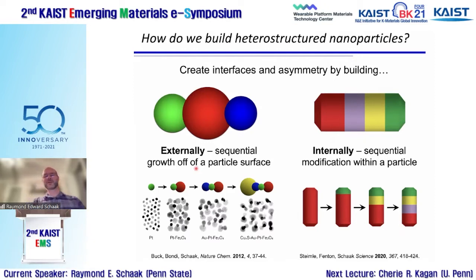But what I'm going to focus the talk on today is a complementary but distinct approach, and that is building interfaces and asymmetry internally within a nanoparticle template. Instead of sequential growth externally, it's sequential modification internally. For this, we use a class of reactions called cation exchange reactions, where we can go in and modify, systematically and in a controllable way, what the inside of the particle looks like.